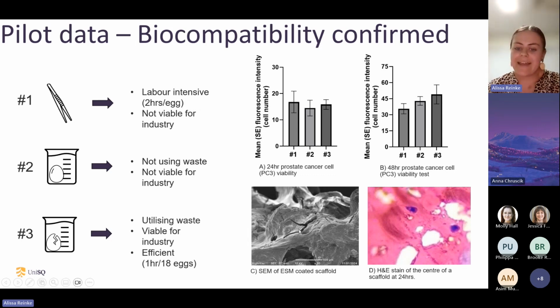I also have checked that the eggshell membrane doesn't just wash off when we put it into the media with the cells. So this is an SEM of the coated scaffold. And obviously in the SEM, it needs to be dried, so it started to crack, but you can definitely see that there is a coating there which remained intact.